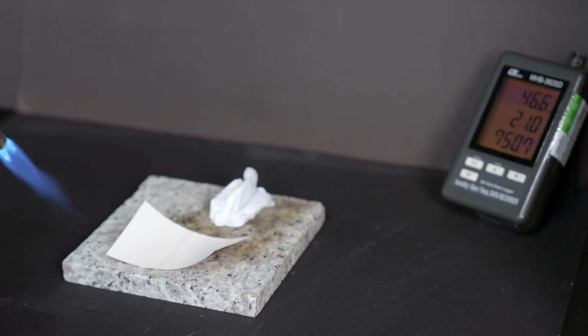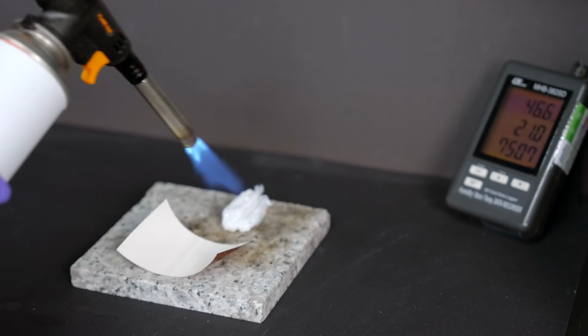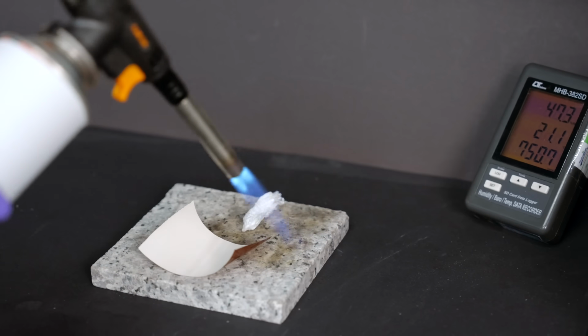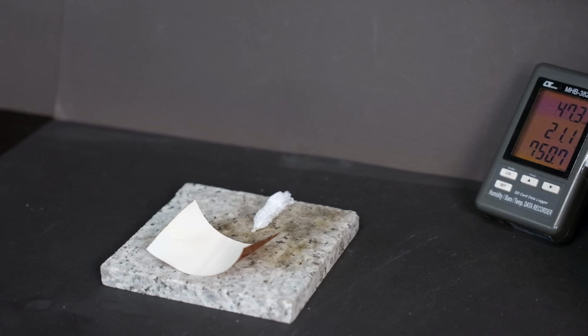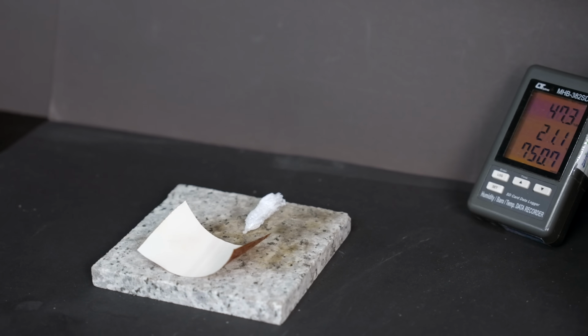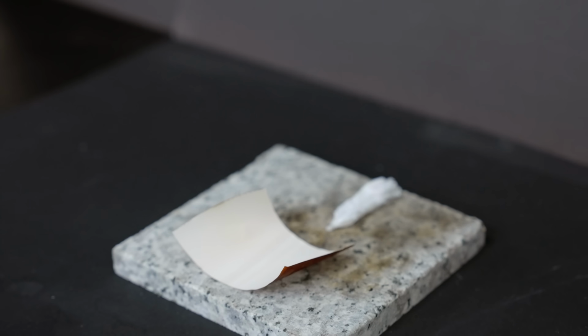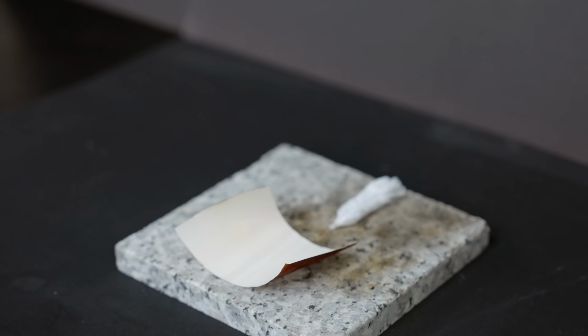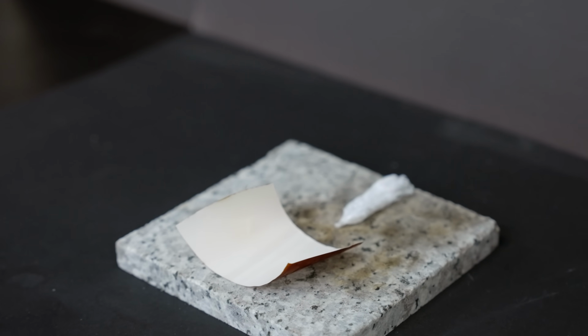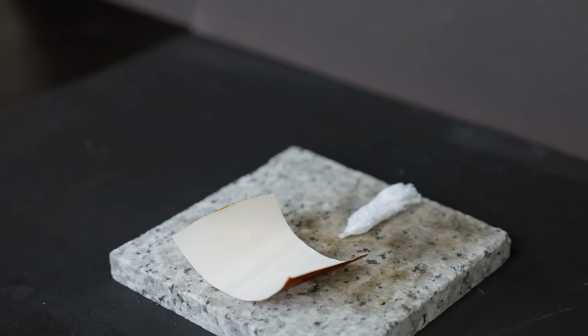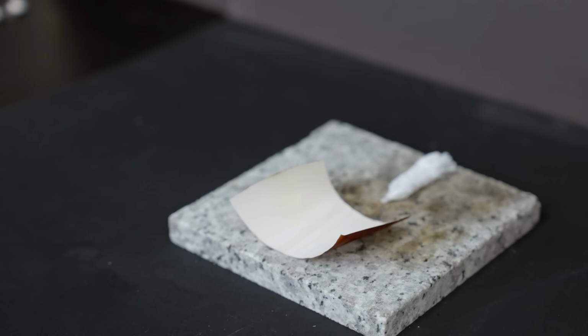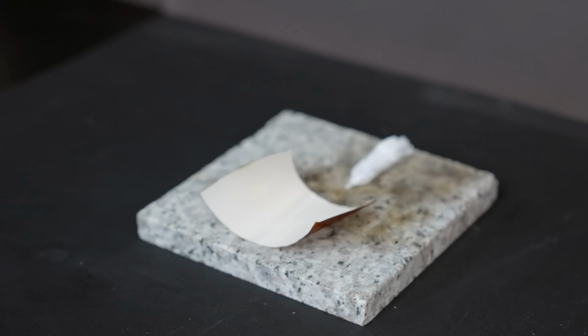Next, we tested the ProLogium ceramic separator against a conventional separator. I used the same propane torch, and you can see immediately the difference between a ceramic separator and a PP polypropylene or PE polyethylene separator. It didn't melt, it didn't shrink, and it didn't ignite. And after we pulled the flame away, the separator was still electrically insulating. It's still doing its job.